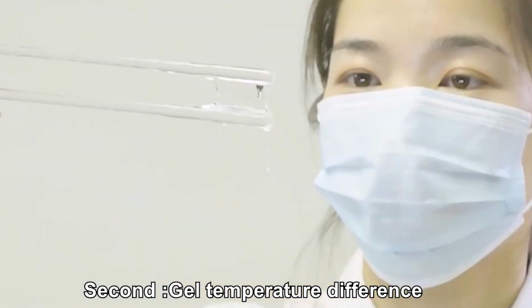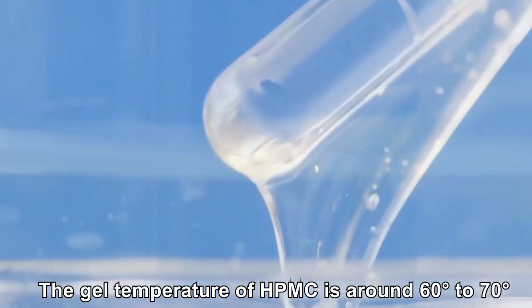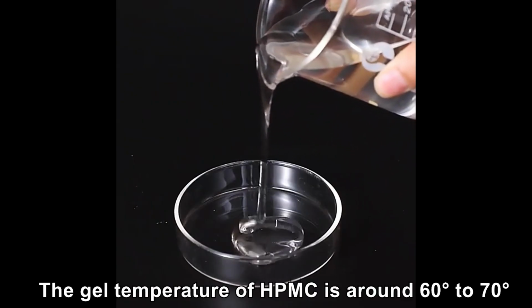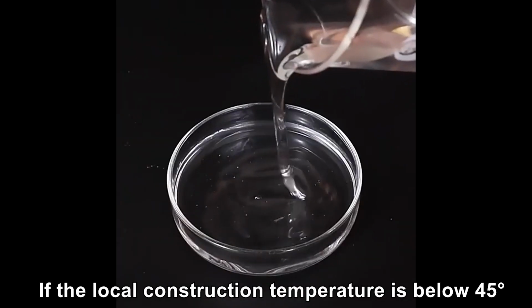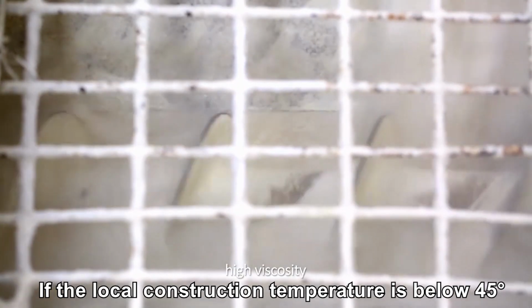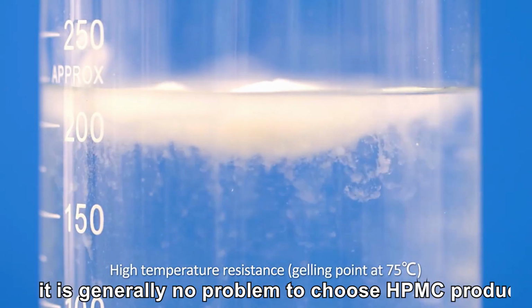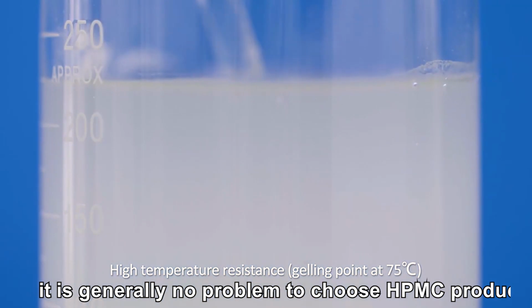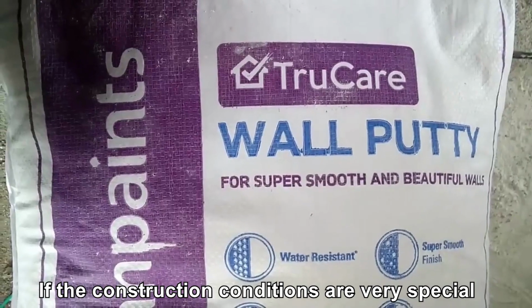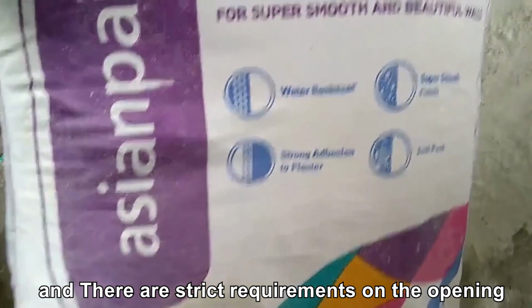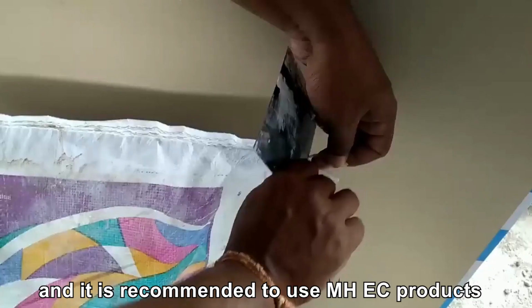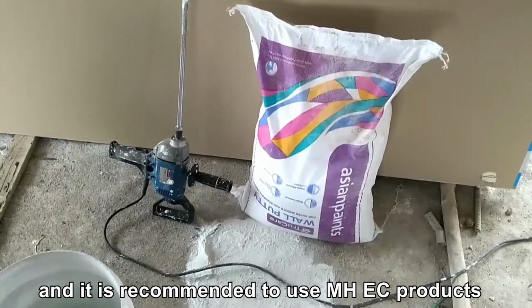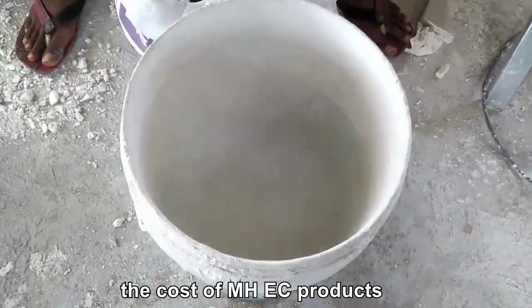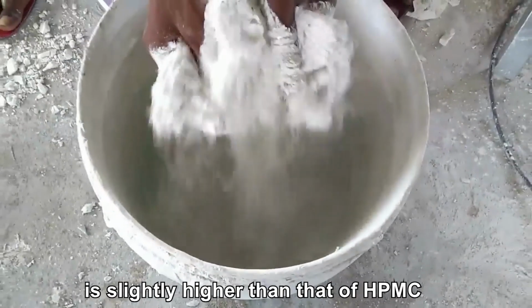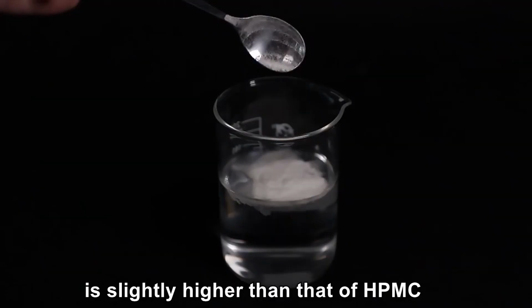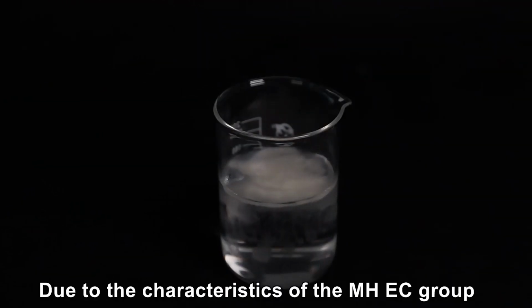Second, gel temperature difference. The gel temperature of HPMC is around 60 degrees to 70 degrees. If the local construction temperature is below 45 degrees, it is generally no problem to choose HPMC products. If the construction conditions are very special, and there are strict requirements on the opening time, it is recommended to use MHEC products. Usually, the cost of MHEC products is slightly higher than that of HPMC, due to the characteristics of the MHEC group.